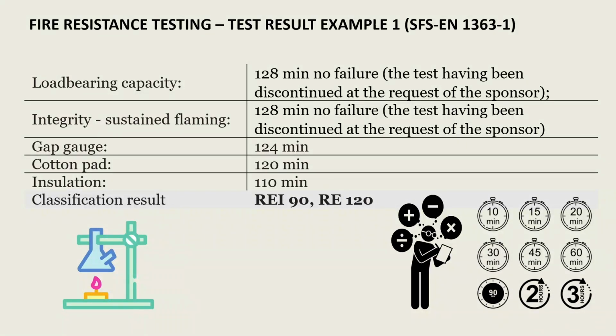So, given all of that information, the classification results can be represented as either REI 90 or RE 120. For REI 90, the specimen satisfies load-bearing, integrity, and insulation criteria for at least 110 minutes. Therefore, 90 minutes is picked as the lowest possible fire resistance rating value. For RE 120, the component satisfies load-bearing and integrity criteria for at least 120 minutes. These classifications indicate the time periods the building element successfully meets specific fire resistance criteria.